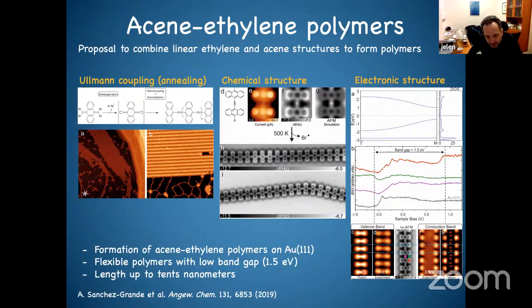And we can compare with the theory. So this is the calculated image of bands. Valence band, and this is the conduction band. So you see that agreement is pretty okay. We can calculate the band structure. So this means that you have 2 bands which have pretty good dispersion. It also gives us some confidence that DFT is not too bad, because using this DFT we are able to reproduce some sort of electronic structure of these guys.